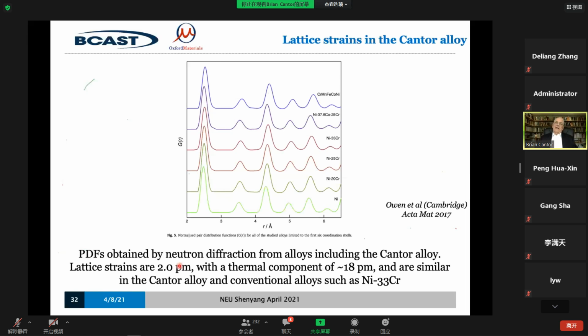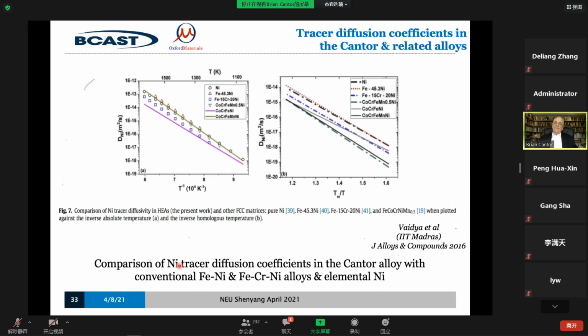I'm going to now talk about the effect of that on diffusion and on slip. The first effect on diffusion is that it stops atoms from moving so easily. They can't move through this strained lattice, which has all these local strains. Most atoms in FCC move by vacancy diffusion. So you have a vacancy, an atom jumps into a vacancy. But as the vacancy moves around, it's moving through very strained lattice. So it's much harder for it to move.